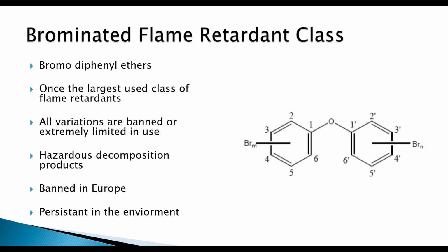The brominated flame retardant class is one of the primary ones that has been a problem, the bromodiphenyl ethers. Decabromo, octabromo, all of these were at one time very common flame retardants, and it was once the largest class of flame retardants around ever. They're additive materials, they're solids, and in and of themselves, they're usually not a problem. The biggest difficulty with these things is the hazardous decomposition products and the fact that they are persistent in the environment.